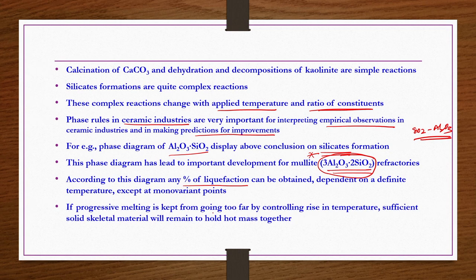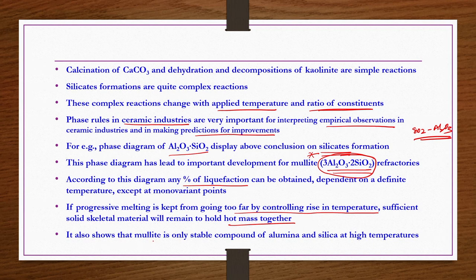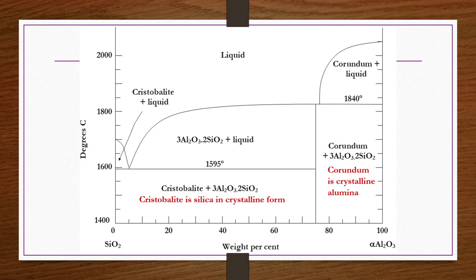If progressive melting is kept from going too far by controlling the rise in temperature, sufficient solid skeletal material will remain to hold the hot mass together. And it shows that mullite is the only stable compound of alumina and silica at high temperatures that you see here in this slide, okay. So, now here we have a pure silica and then a pure alpha alumina. Now, if you have pure silica with less than 10% alumina mixed with the silica, then you know what happens? Liquid and then cristobalite. Cristobalite is nothing but the crystalline form of silica. That you can get if you operate at a temperature more than 1595 degrees centigrade, right.